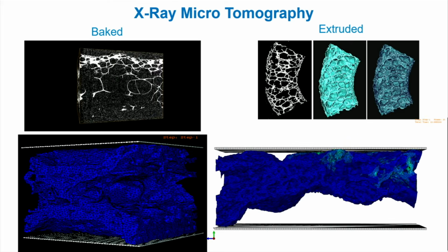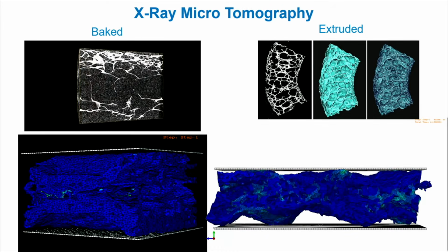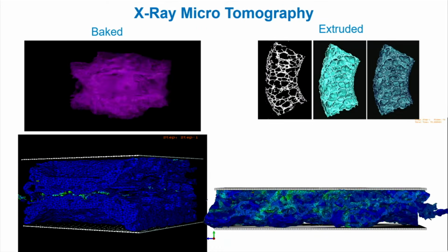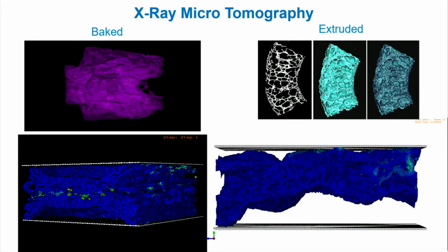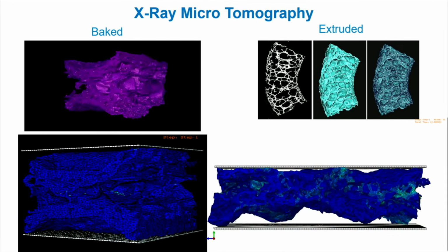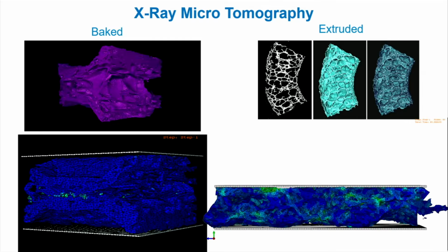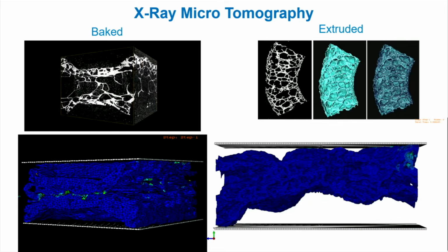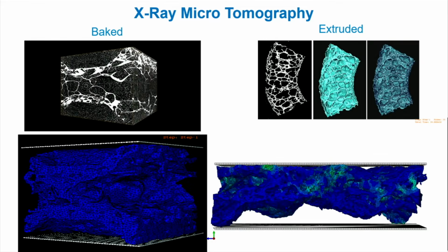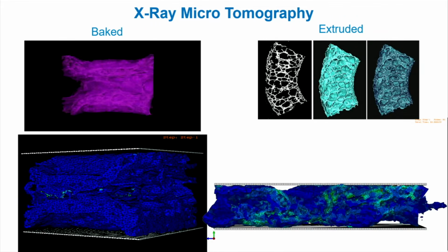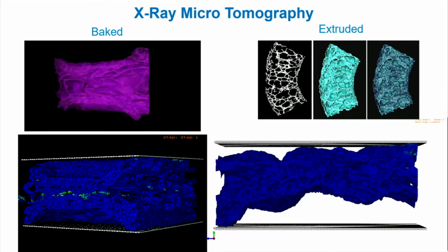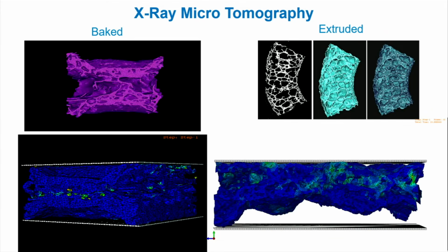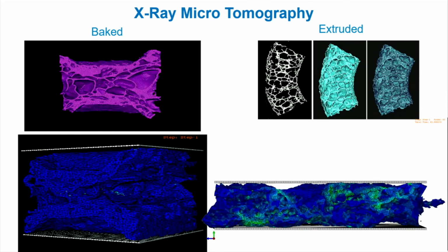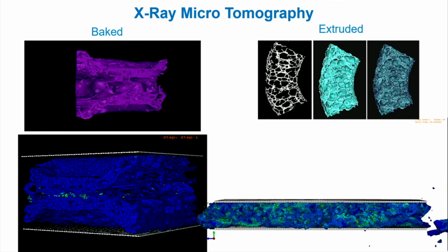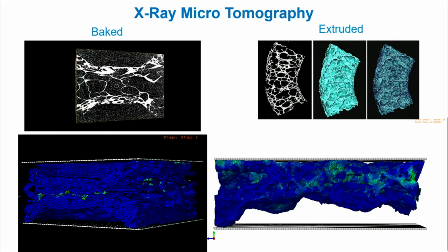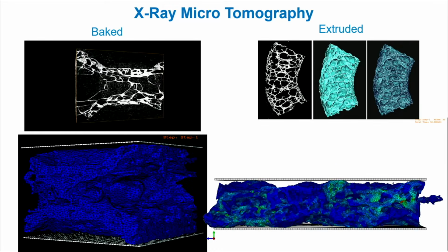So to find out what the differences are, we take the three-dimensional images from X-ray tomography, and we use them inside computer simulations to do virtual compression tests. We get the output from these models, and then we see what mechanical properties I have to put on the solid that makes up the thin cell walls, such that the output of these models is the same as the experiment. And this gives us a measure for the properties of this solid cell wall, which otherwise would have been very difficult to measure.